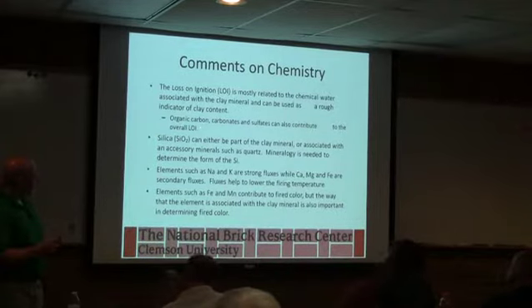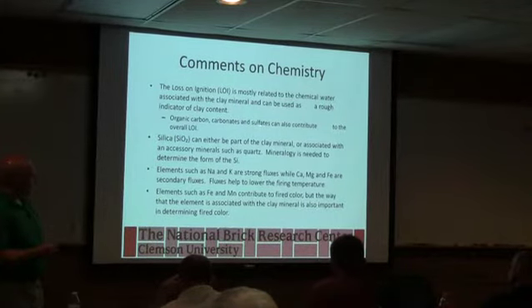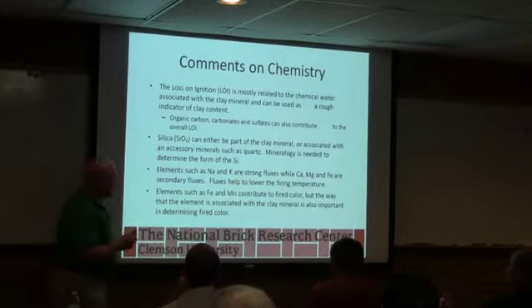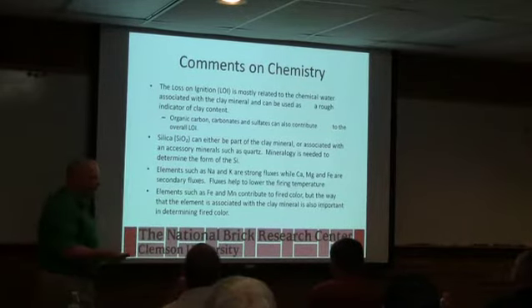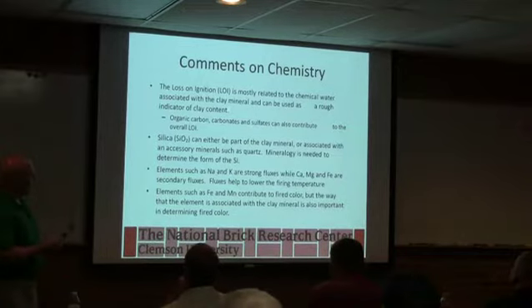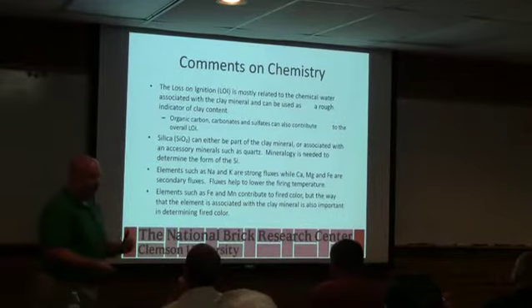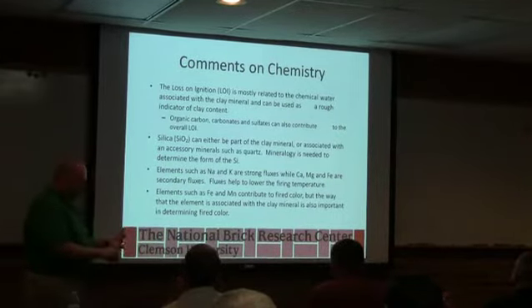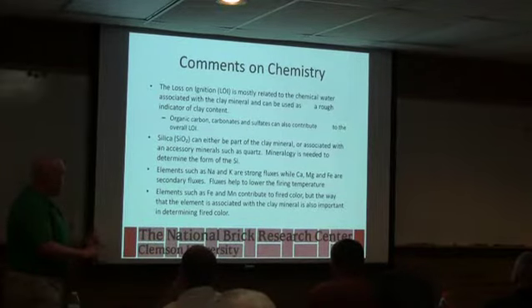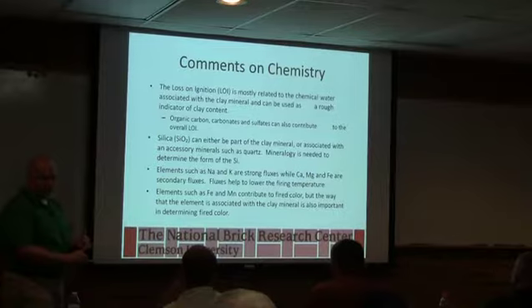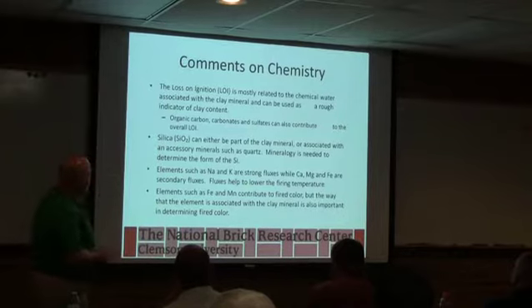It also can give you information about organic carbon, carbonates like calcium carbonate for lime pops. It could give you information about sulfates we haven't really talked about yet. But they all contribute to that overall LOI. So just because you see a high LOI doesn't mean it's a high carbon or it's got limestone. There are too many things that go into it. It's another easy quality control tool. So you can watch it over time, and if you're seeing changes, then you've got a clay change or one of your accessory minerals has changed. So it's a good, easy tool to see if the material's consistent.